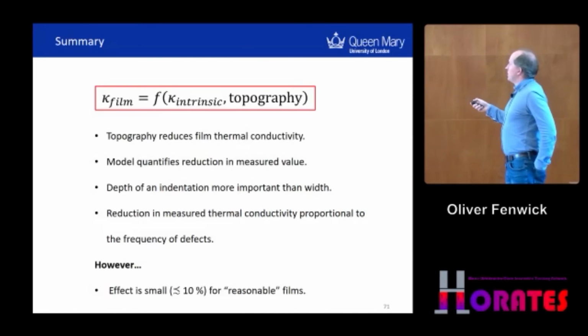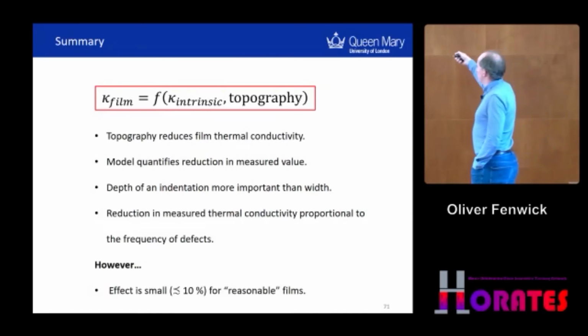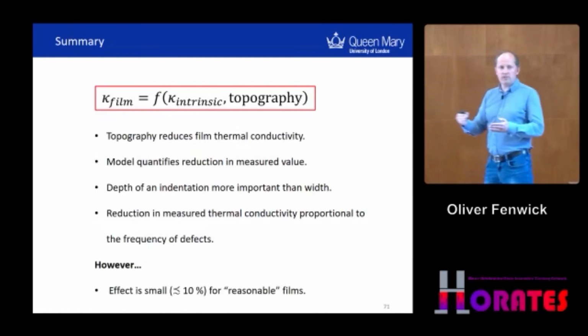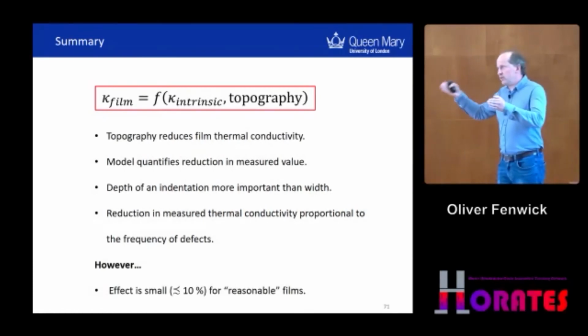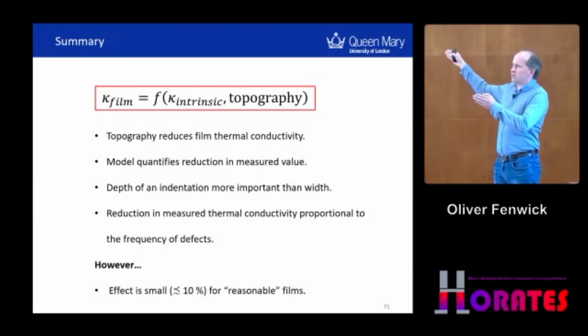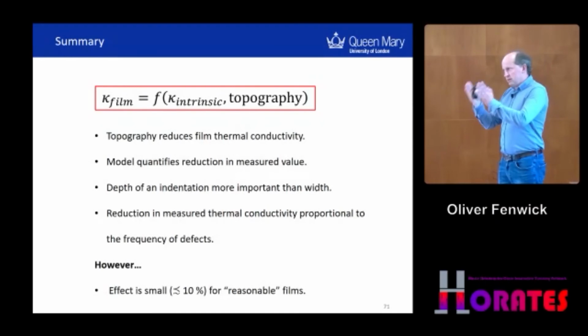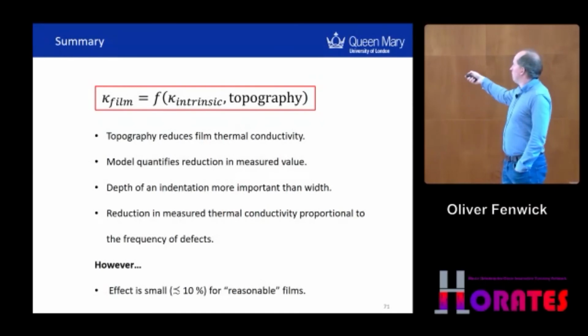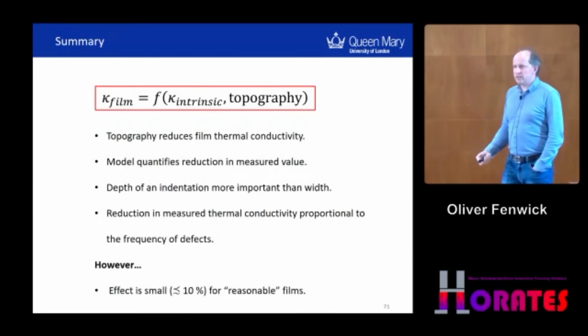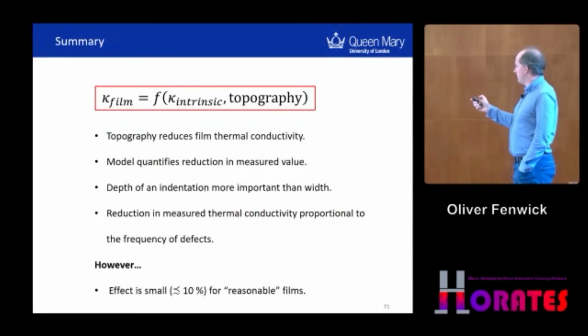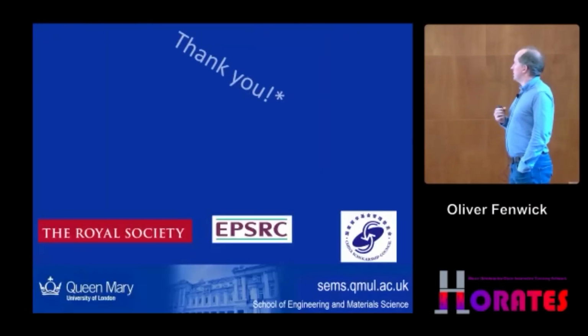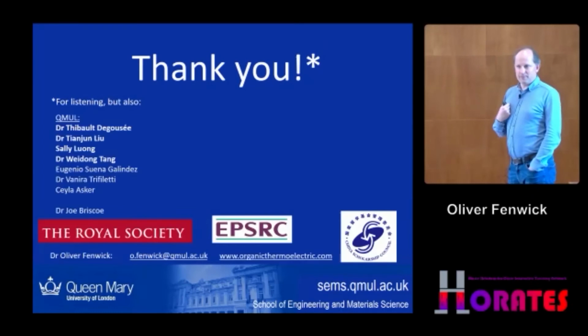Other things that came out of this modeling, which I'm not showing today: the depth of an indentation seems to matter more than its width. The reduction in thermal conductivity is proportional to the frequency of defects. We put in a defect every 1.5 microns to match our experiment that we're still working on. If you make one every 1 micron, it will be more. However, I think the good news is that this effect is small for reasonable films, but you need to be alert in case you have very high topographies. I think that's it. Thank you.